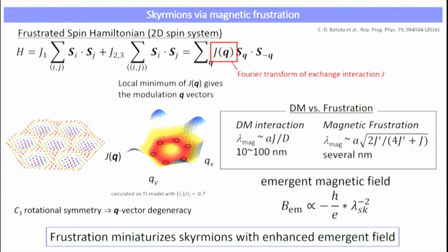There are two different types of Skyrmions, which have a different helicity, a kind of handedness of the spiral structures. But the handedness doesn't affect the sign of the topological Hall effect. Both of them have the same topology. So the handedness doesn't affect the magnitude of the topological Hall effect, even in the case of the centrosymmetric frustrated system. But no twist, no Skyrmion? No twist, and no Skyrmion, I think, yeah.